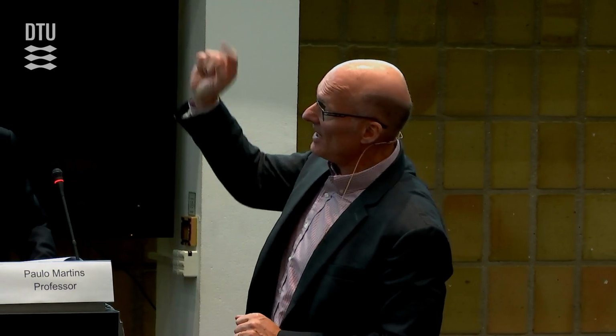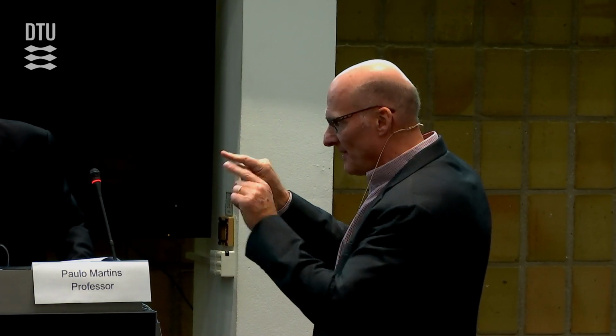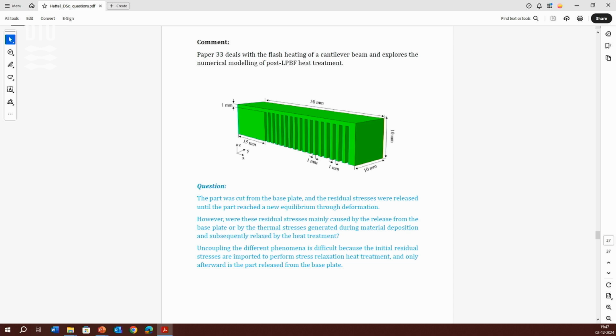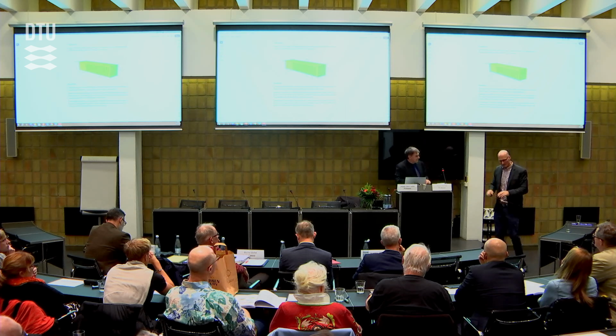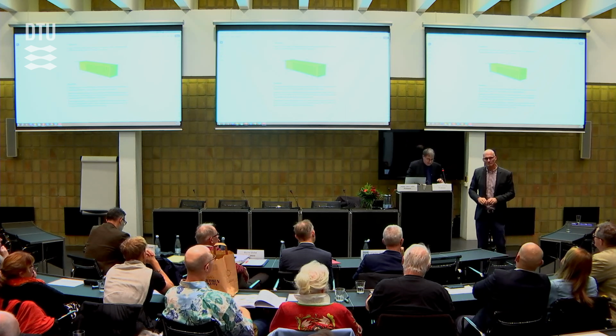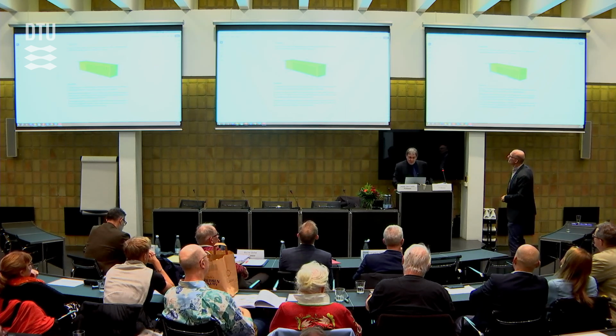And the way that we evaluated this was that we compared that residual stress calculation of the AM simulation, before the heat treatment, with the experiment of the tip deflection. Before releasing. Okay. And then you compare after releasing again. Okay. So that was my question. That was the way I would do it. Yeah. Okay, good. Very good.